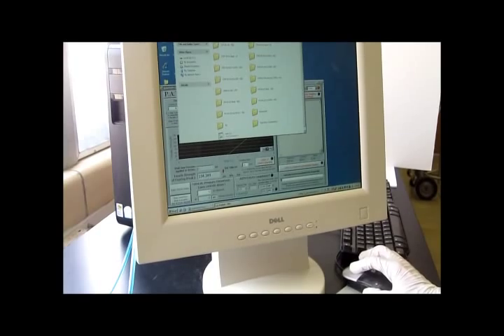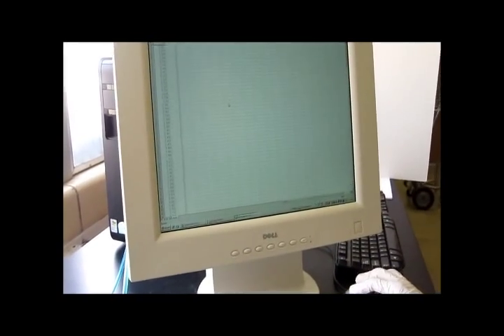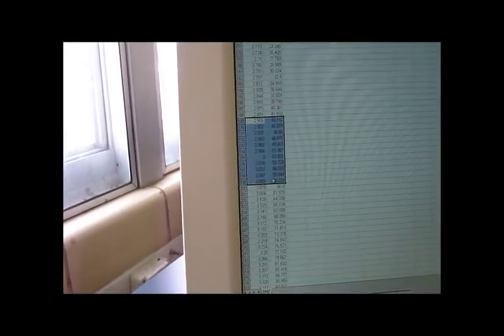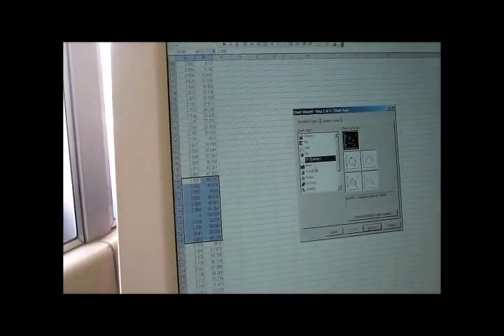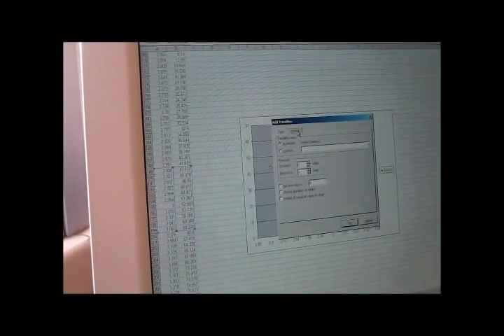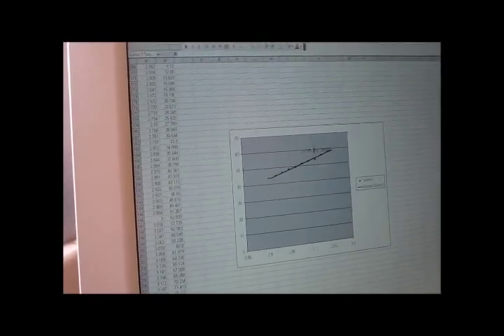The text file from the results is then opened in Excel and a portion of the loading data is selected and a linear trend line is applied to the data. The loading rate is the slope of this line, which should be equal to 100. If the loading rate is different, repeat the test after adjusting the flow rate of the machine.